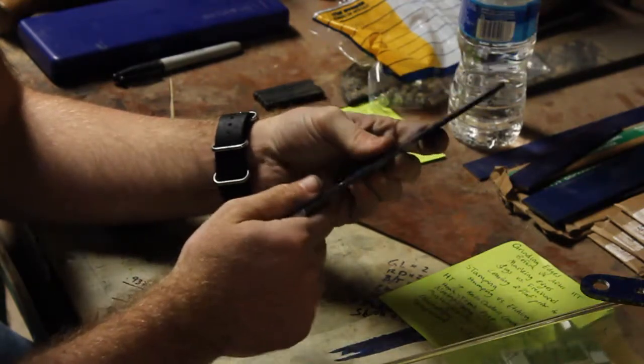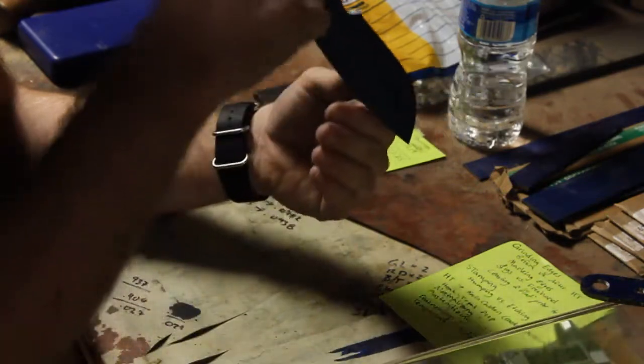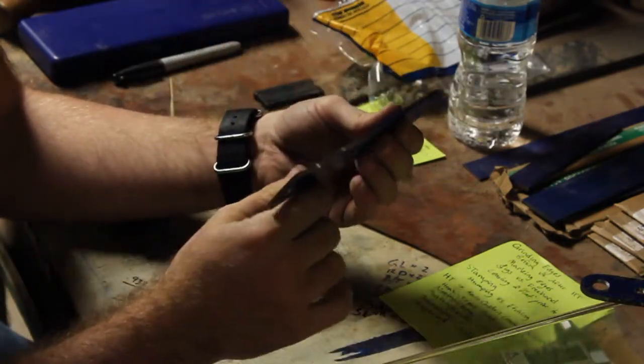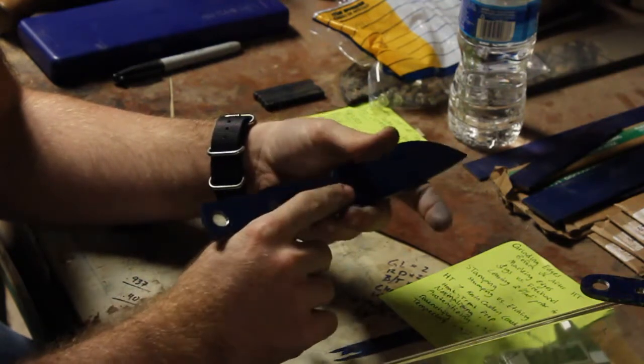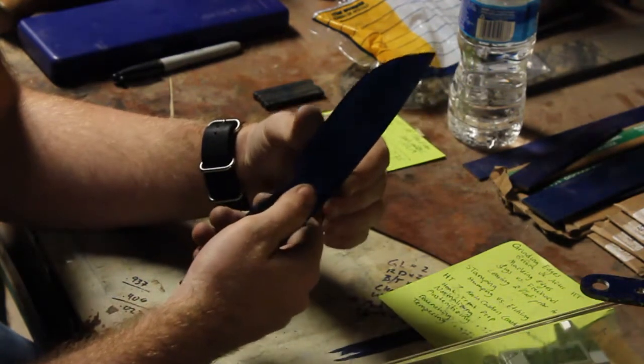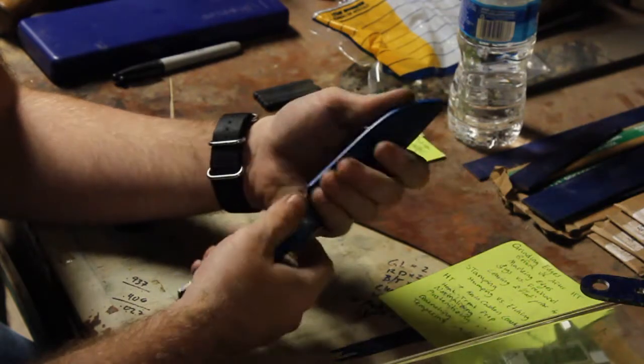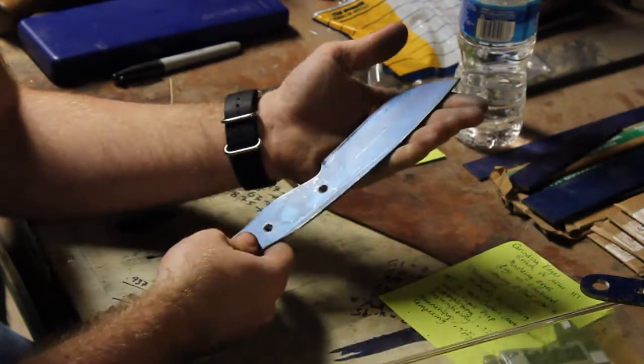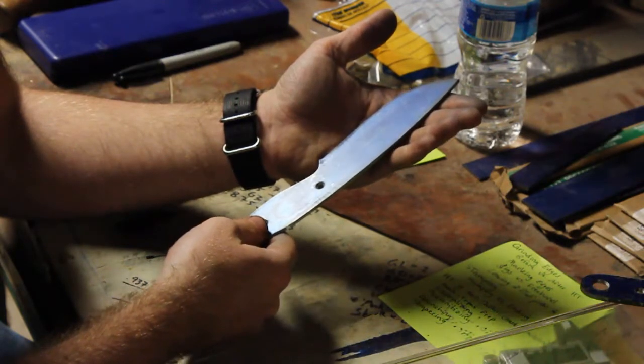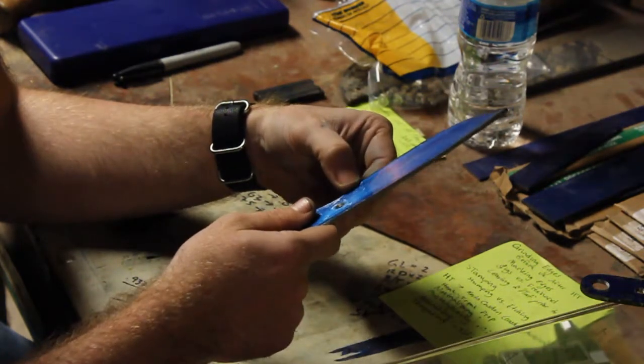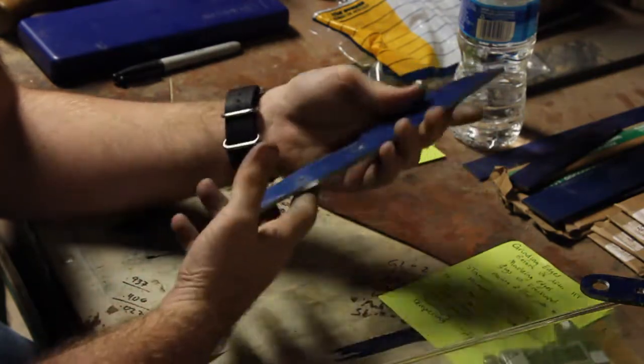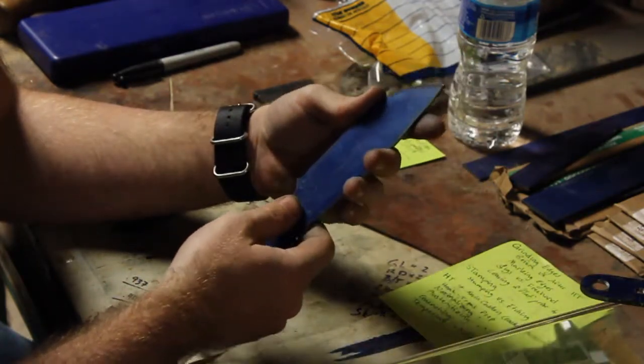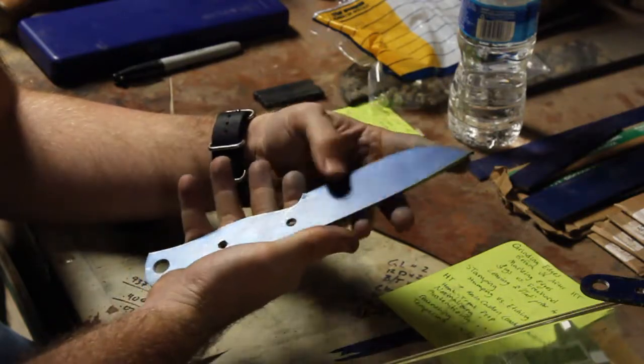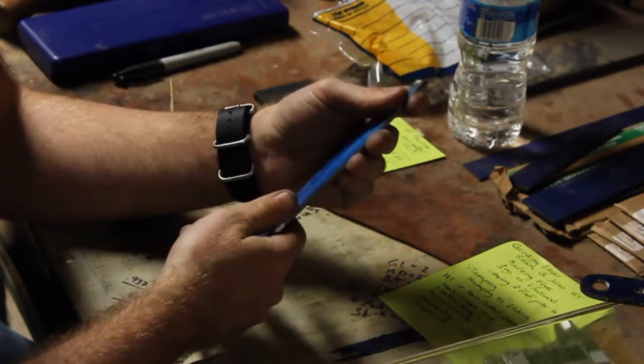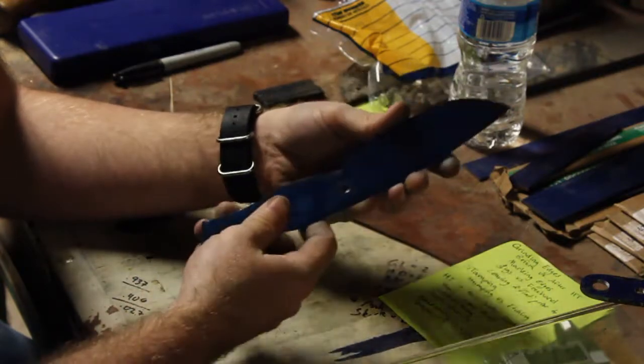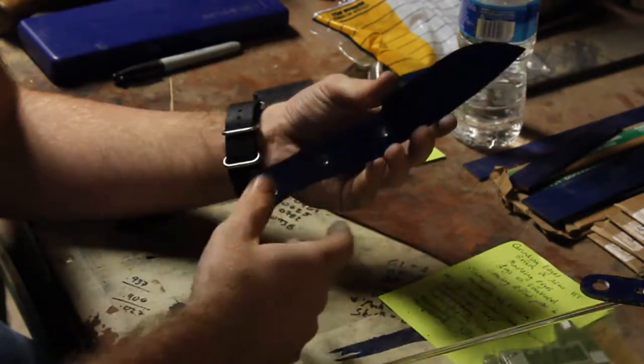After it's soaked for the allotted amount of time, it's pulled and quickly quenched. My quenching oil is preheated to between 130 and 150 degrees Fahrenheit, and I use Chevron 70. And you want to quench long enough too. You want to make sure that you're not just dunking it and then pulling it back out and throwing it aside. So do some research if you're looking to heat treat your own blades, and make sure you know how you should be quenching them or what temperatures that you should be using, etc.